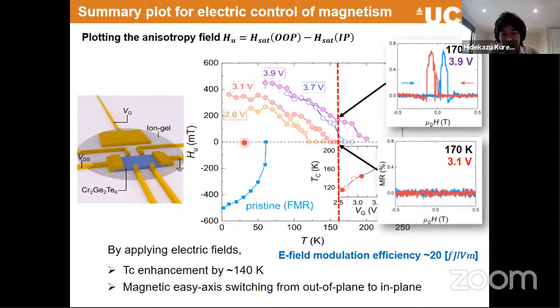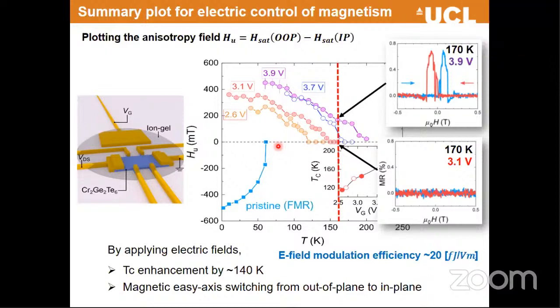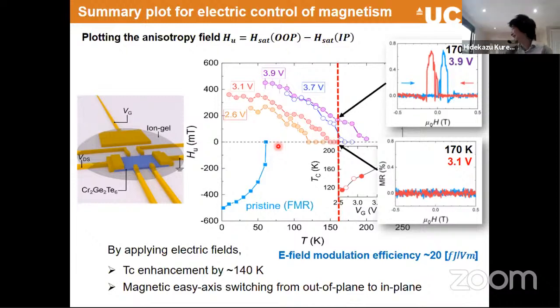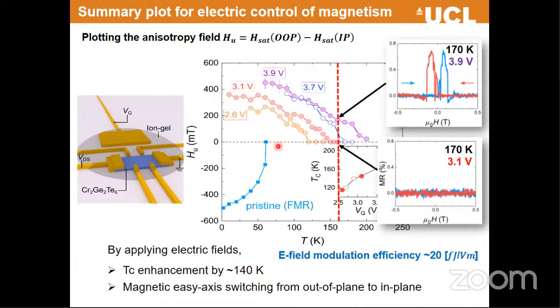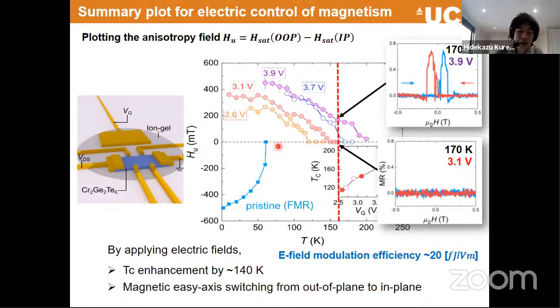It's not a significant jump from one to the other. There is some transient between these two switching. So the value of the uniaxial anisotropy is gradually changing through zero. Can you also reach this regime of almost zero anisotropy for very thin films, for 1-2 layers? Because my idea was maybe at that regime you generate